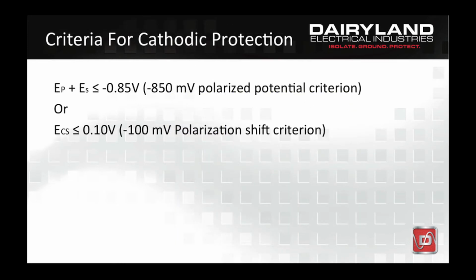Next, let's review the requirements for a pipeline to be cathodically protected. According to NACE criteria, one of the two conditions listed on this slide must be met. The above terms were described on the previous slide except the term labeled E with the subscript CS, which pertains to the 100 millivolt shift criterion. Of these two criteria, the more commonly used with modern high-resistance pipeline coatings is the minus 850 millivolt polarized potential criterion, which is a measurement typically taken within a fraction of a second after the rectifier current is switched off.